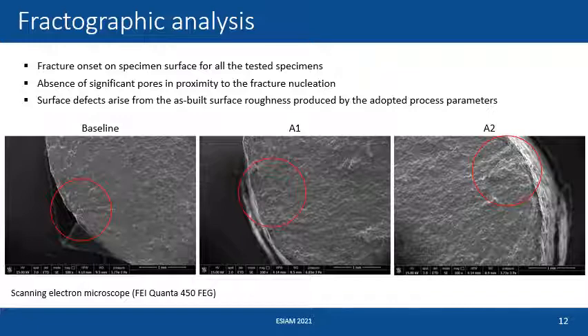But we can see that near the surface, for each crack nucleation, there are some superficial defects that almost tend to the surface roughness of the specimen, which seems to play the most important role in affecting the fatigue crack nucleation and the fatigue life of the specimens for the three sets.